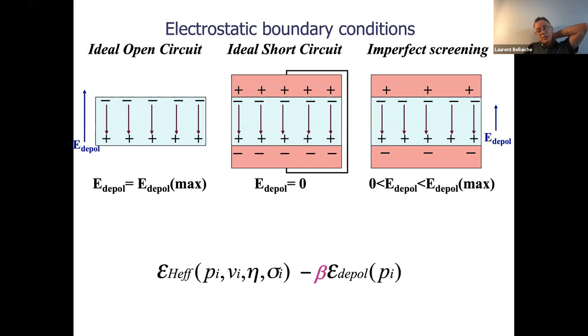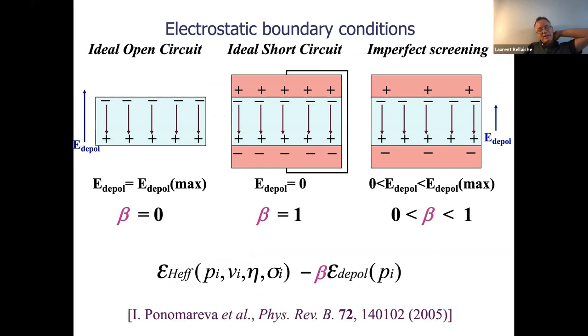So how did we do that? Ponomareva, Ivan Naumov, and Sergey Prosandeev found a very smart way to do that. It's a little bit technical, but I refer you to the paper indicated here, a PRB of 2005. The idea is quite smart in my mind: for any low dimensional structure, wires, dots, superlattices, so 0D, 1D, or 2D, let's say films, you calculate the dipole-dipole interaction. For example, in 0D, you do that in real space. In 3D, you do that in reciprocal space. But between 1D and 2D, it's a kind of mixture between real space and reciprocal space. And you compute the maximum depolarizing field. Let's call that epsilon depol. And then you put a coefficient that we call beta. Beta equals zero, which means you have a perfect open circuit boundary condition.